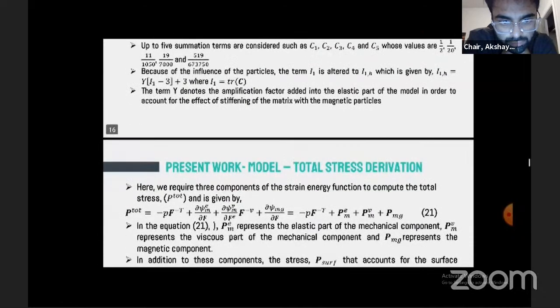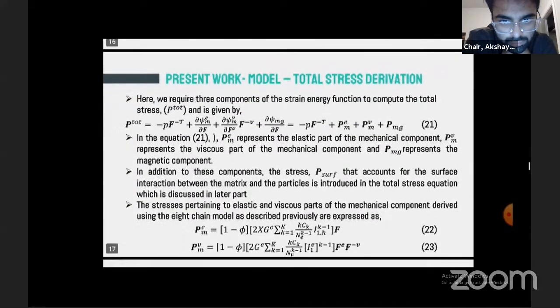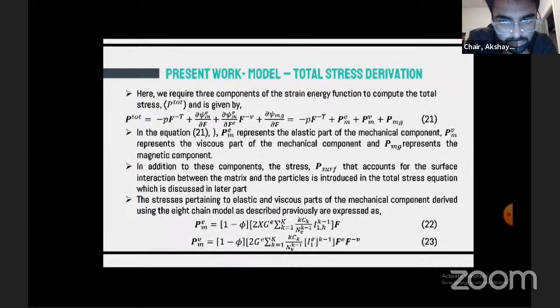Followed by the mechanical part, the total stress derivation using the magnetic and mechanical part will be defined here. Using the above mentioned equations, the total stress is given by the summation of the terms shown in equation 21. The equation is composed of the elastic part, viscous part, and the magnetic part. In addition to these components, the surface energy concepts will also be included, which I'll discuss in the later part. The surface stress that accounts for the surface interaction between the matrix and the particles will be introduced.